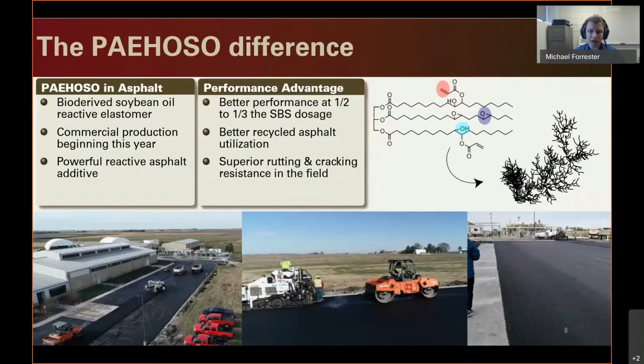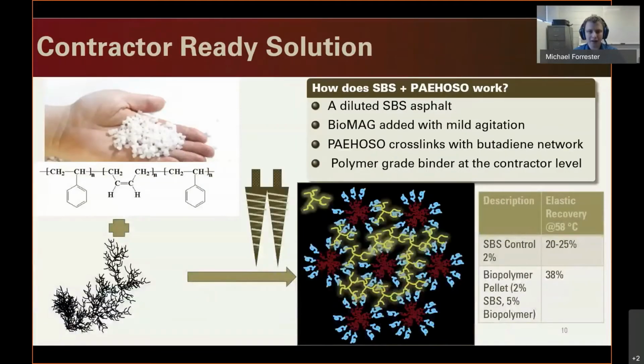In addition to that, because the biopolymer system is so chemically reactive, it actually rejuvenates a lot of the aged asphalts that are typically used in recycling. And so with this technology, you can actually use a high degree of recycled asphalt and still get high polymer quality paving roads. So you might ask, why does this matter in the world of compounding?